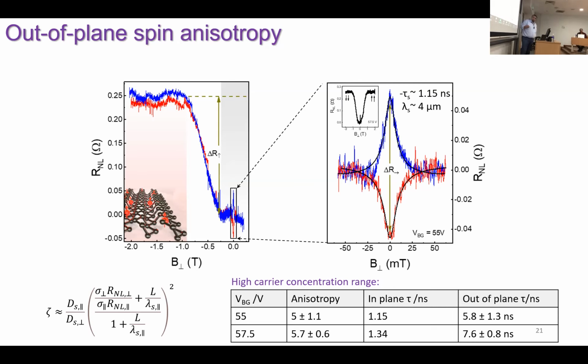And here we did the negative field, but if you do also the positive field, basically they go to the same value. It's just because either all of them are fully out of plane or in plane. So they are parallel in both cases. So it doesn't make any difference.